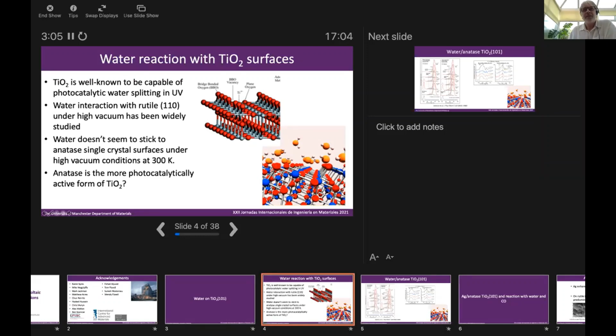And the reason that anatase hadn't been so well studied was mainly due to the availability of single crystals. But over the last 20 years or so, we've been able to get hold of these single crystals. And so one of the early experiments done in these UHV studies, what tends to happen is you prepare your model surface, get it atomically clean. You then expose it to maybe 10 to the minus 6 millibar of water vapor, or whatever gas you're interested in.